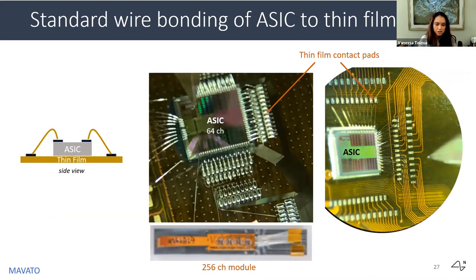One way is to directly bond the pads on the thin film to the stimulation and recording chip, or the ASIC. So here I'm showing a standard wire bonding process. Wire bonding uses ultrasonic energy to bond metal wires to metal contact pads on the ASIC and pads on the thin film. So if you look at the drawing on the left, pads are designed on the top of the ASIC and then are wire bonded down to the pads that you've designed on the thin film.